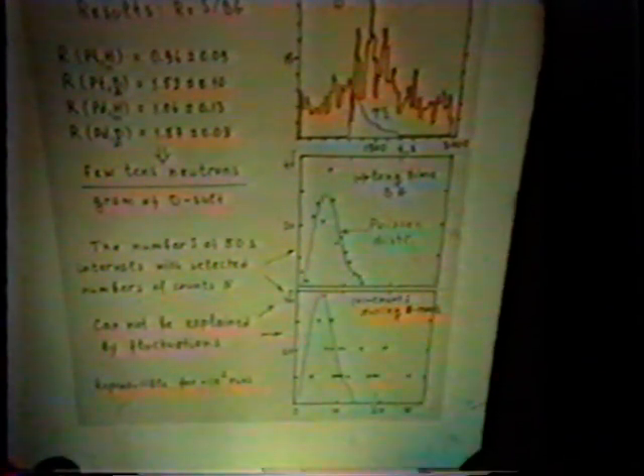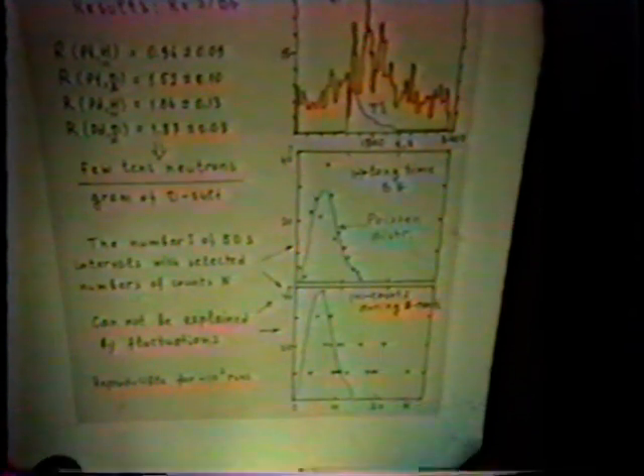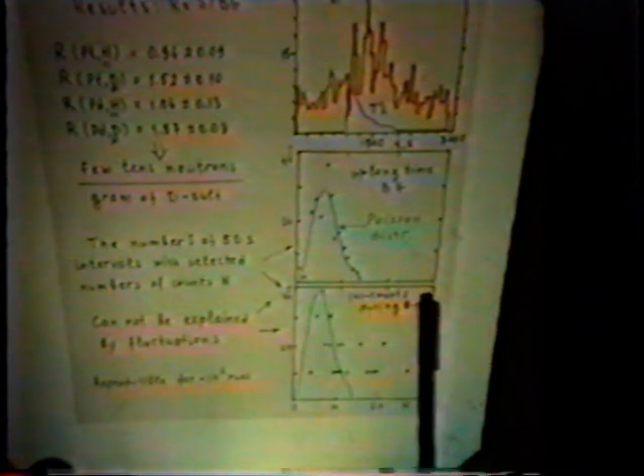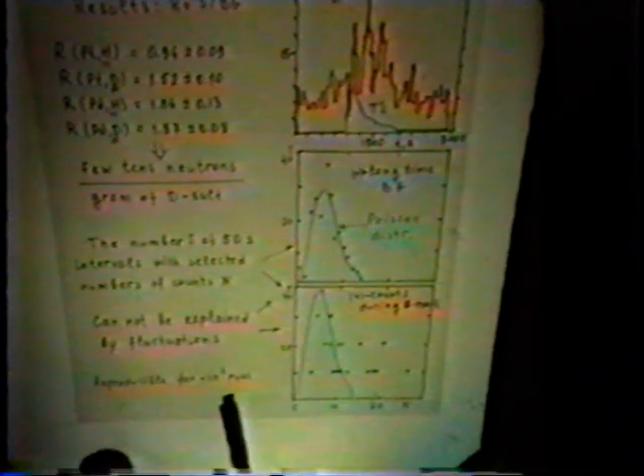Here you can see the results of long-time background measurements, which follow a Poisson distribution. And here are the results taken during reactions with the deuterated source, and you can see the excess here. Another feature is the high reproducibility of these experiments.